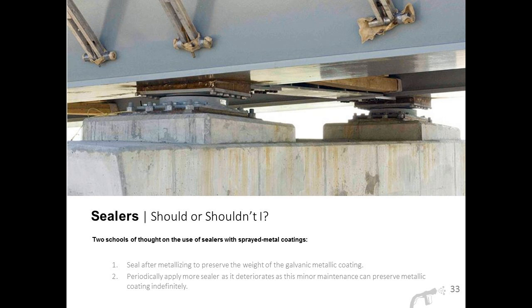First is to just apply the sealer after metallizing and allow it to preserve the weight of the galvanic metallic coating. No maintenance is needed for decades, but eventually, after 10, 20, 30 years, the sealer is going to break down. In the meantime, when the sealer is in place, less metal is consumed by oxidation than if the metallic coating is left bare. Once the sealer is gone, that's when the metallized coating starts to do its job by corroding slowly over time, protecting the steel. The sealer extends the life of the coating for the relatively low cost to apply it.